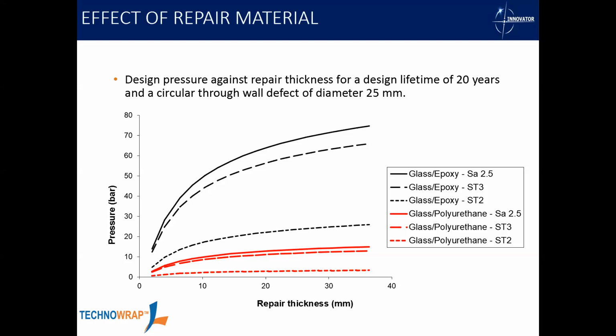This is under certain design conditions. It's a 25 millimeter hole, 20 years. You'll get a design thickness of 10 millimeters for about 50 bar pressure for grit blasted. If you then reduce the surface preparation to bristle blasted, so ST3, at that 10 millimeter repair thickness you're getting probably about 40 bar pressure retention. So a 20% reduction just from changing to a bristle blasted surface prep from grit blasted.